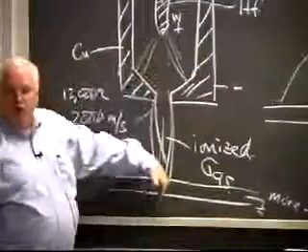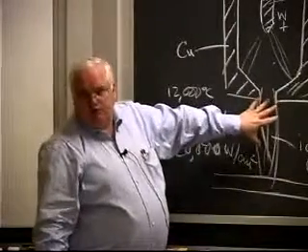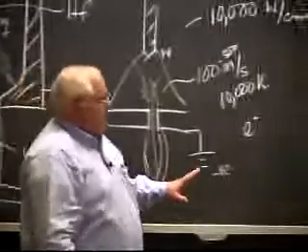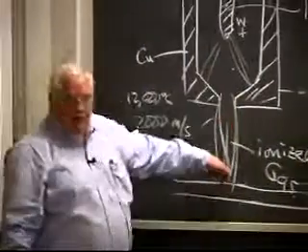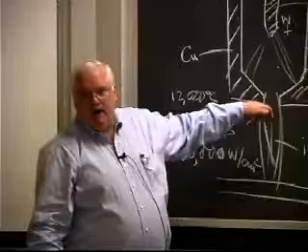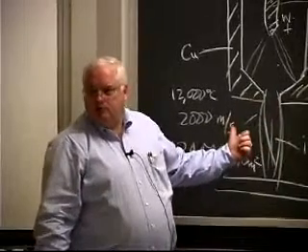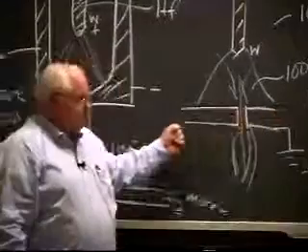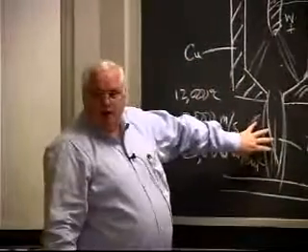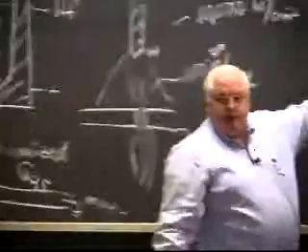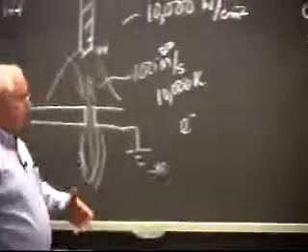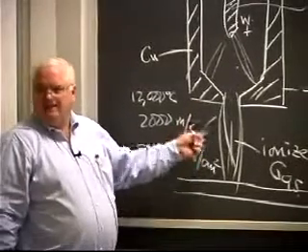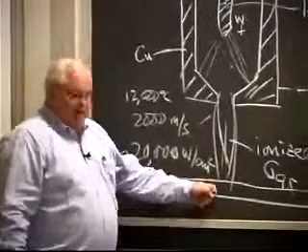So I actually carry current through here, and this is called the transferred arc process. And so yes, the workpiece does have to be conductive. It turns out that if I were to run this process and not carry current through here, I would get about 2,000 watts per square centimeter, not 20,000. Why? Because 90% of the heat in the arc process is carried by the electrons, only 10% by the hot gases. I have hotter gases and higher velocities here than I have over in this process, but if I'm not carrying the current, it's only a doubling of the oxy-fuel process. It's not a doubling of the arc process unless I carry current here.